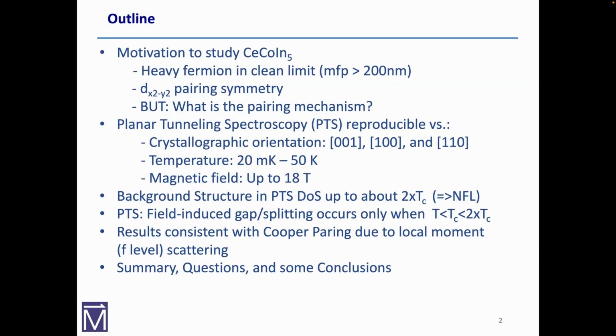I won't have time to go into this now, but in planar tunneling spectroscopy, if you see something that doesn't look like Ohm's law, it's non-Fermi liquid. I'd be happy to go over Harrison's theorem with you, but basically the fact that we see structure above TC tells you, just like almost all the other unconventional superconductors, that it's non-Fermi liquid above TC. We also see background structure reproducibly up to about twice TC, not much higher. TC is 2.3 degrees, and we see this structure up to about 5 degrees.